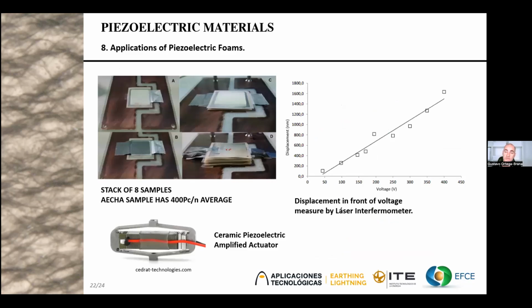This is one of our setups. Ceramic actuators have been used in piezoelectric stacks, because they multiply the effects of each of the piezoelectric devices. In the photo below, we can see an actuator made from multiple ceramic piezoelectric devices. We made an actuator from piezoelectric polymer foams, with 8 samples with a d33 constant of about 400 picocoulombs per newton, stacked together. In the graph on the right, we can see the measurements when we apply an electric field and measure the displacement with a laser interferometer, showing how linear the behavior of the stack is with this material.